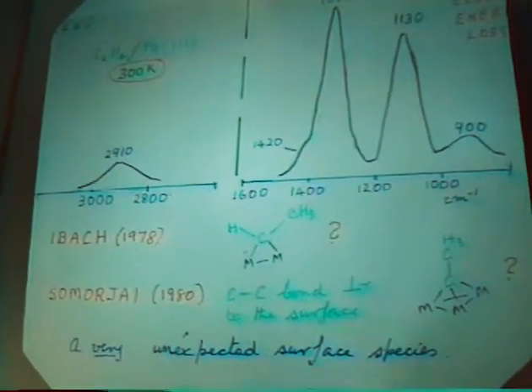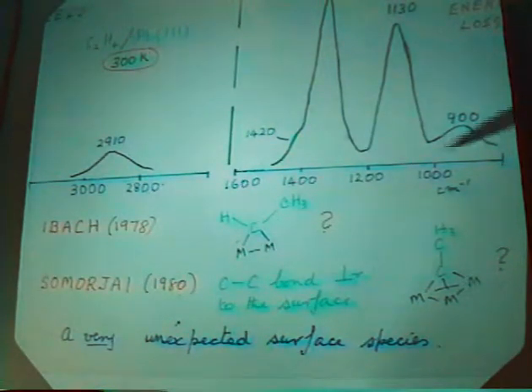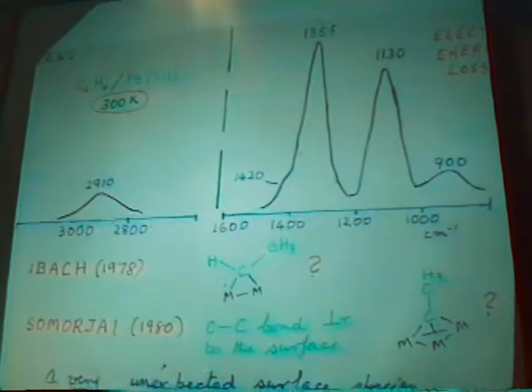And then Somorjai and his group in Berkeley did low-energy electron diffraction and showed that the C-C bond was perpendicular to the surface. Well, if that's the case, yes, the CH3 group is entirely possible. You immediately think in this type of arrangement. And I knew enough, being a chemist, about the literature to know there was a metal cluster compound which had that species on it.